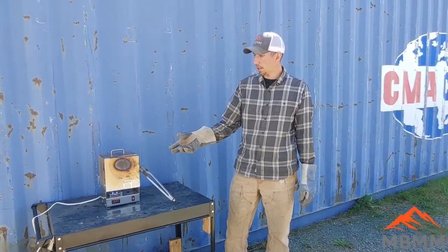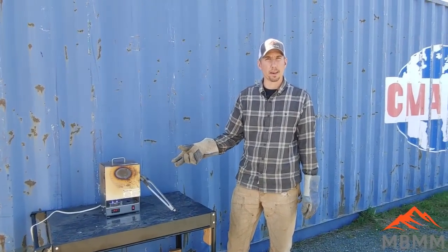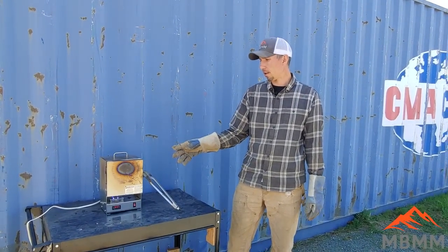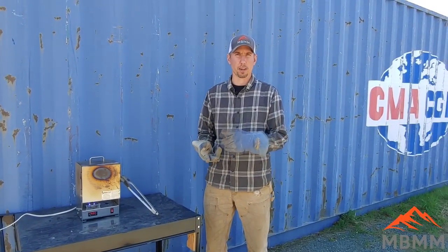So this is our little electric furnace that we're using to cupel our lead. We have our 3 samples in there, our 50 plus, our 50 to 100, and our 100 minus. What actually goes on here with the cupelling process is the cupels are made of bone ash, or I think it's magnesium oxide, which is porous to oxides, but not to metal. So you put your lead metal, the collector metal from our smelts, in your little dish. As you bring it up to temperature, the lead melts at about 650 degrees or something.